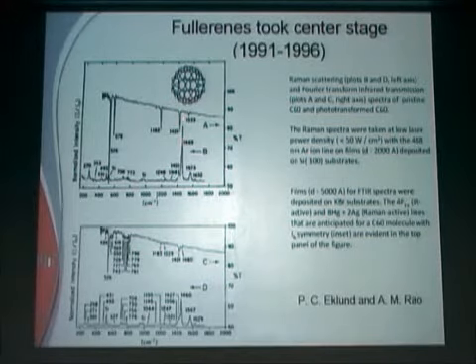With low laser power to make these clusters, the infrared spectrum was kind of simple and the Raman spectrum was not so complex either. Each one of the peaks that we observed could be explained in detail. Then we used higher laser power, and you can see that there were many, many lines — in fact, 200 or so infrared and 200 Raman modes. The reason for that is that you have a molecule so extremely symmetrical that you have so many allowed transitions, and they can make combination modes and harmonics. In the book we actually identified all of these. It was the most amazing thing to do solid-state physics and molecular spectroscopy at the same time.